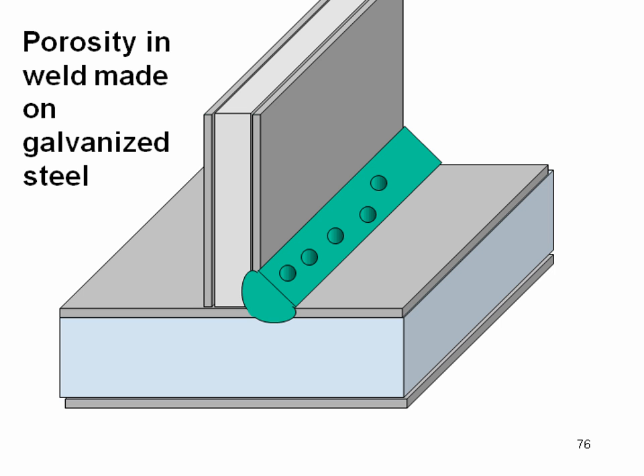If you've ever welded on galvanized material, there's a lot of fume that's generated, and that fume percolates through the weld. And if, when it's going through the weld, it solidifies, you can end up with holes in your weld. Now, for structural applications, we do have acceptance limits for porosity. We're allowed to have some. We're not allowed to have a lot. And so that may be one of the problems you encounter.